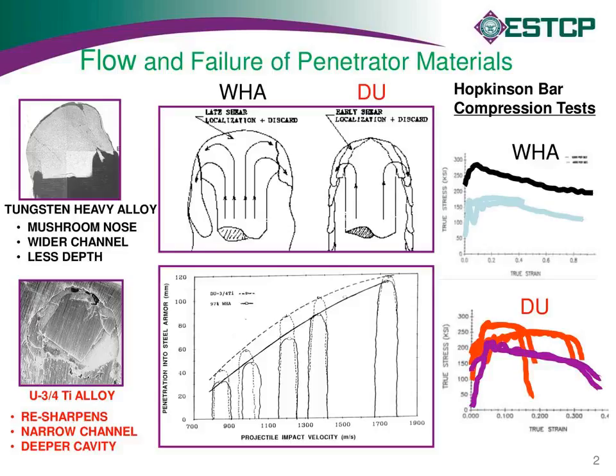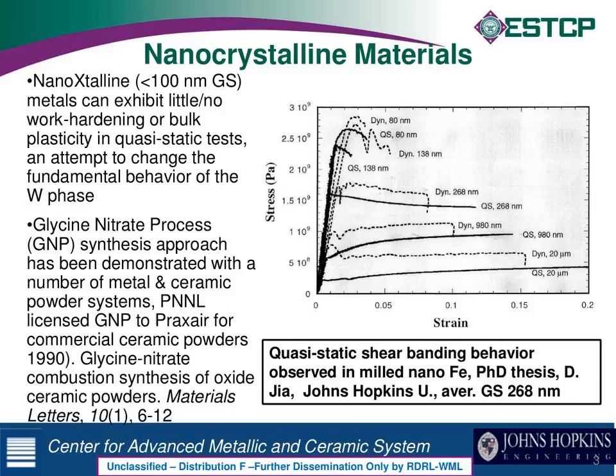The next slide, which would be slide 3, shows why we were taking this approach with a nanocrystalline version of tungsten heavy alloys. In general, nanocrystalline versions of all materials tend to be stronger, tend to have less strain rate sensitivity, which is another thing that can tend to keep things plastically stable, and have less work hardening capacity because you've made them so much stronger. And so there's a lot of basic reasons why a nanocrystalline version of almost any metal is going to tend to become more and more plastically unstable.